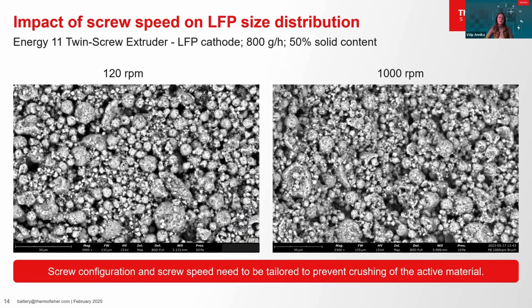Here you see an LFP cathode. The LFP size distribution was widened and decreased because this screw design led to breakage of the LFP particles. The effect increases with higher screw speed due to higher shear, and it's probably not a wanted effect. These 2 examples show that the screw design and the speed needs to be adapted to the specific materials.